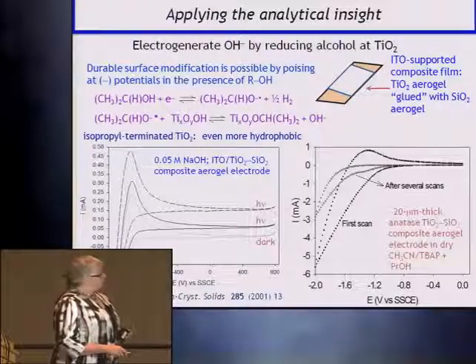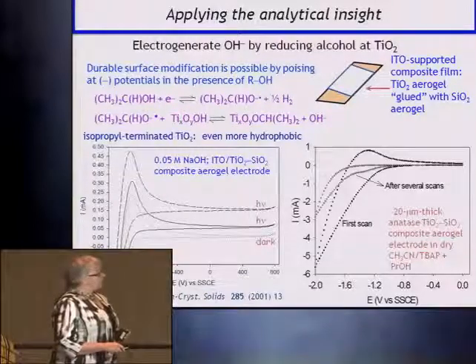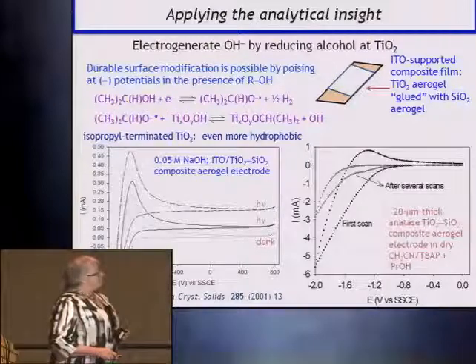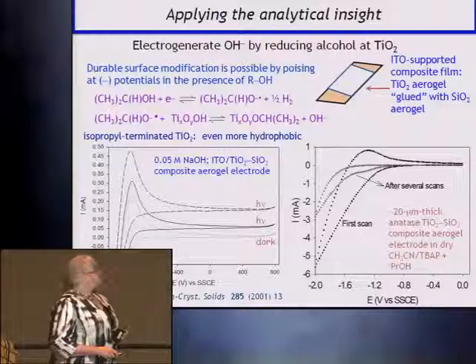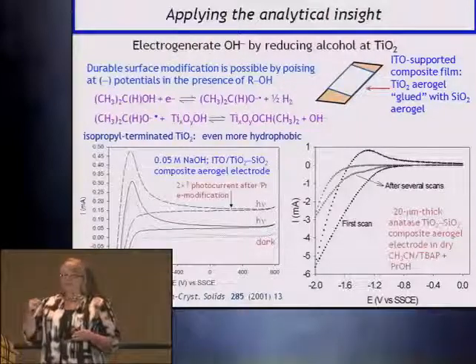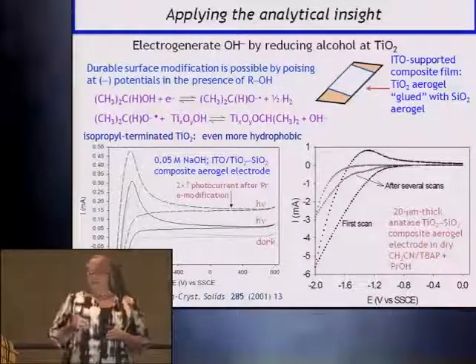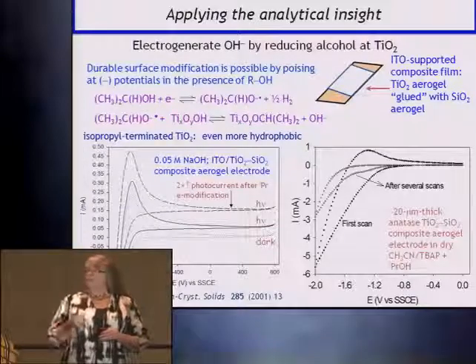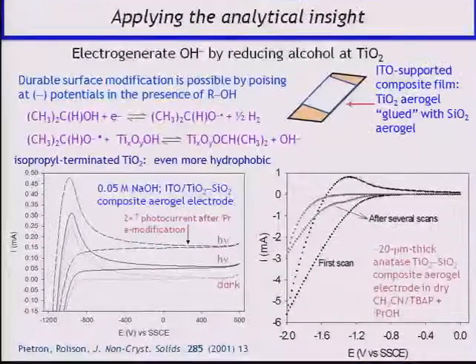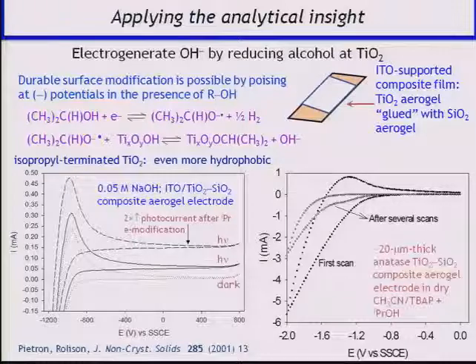Dark photocurrent, we're now in water with sodium hydroxide. This has not been modified, that's the dark current. This has not been modified, that's with light. But you put the isopropanol grafted onto the titanols, healing those defects, you double the photocurrent. So again, the kind of information we got from analyzing titanol-rich titania immediately allowed us to look at a different way to improve this system as a photoanode.